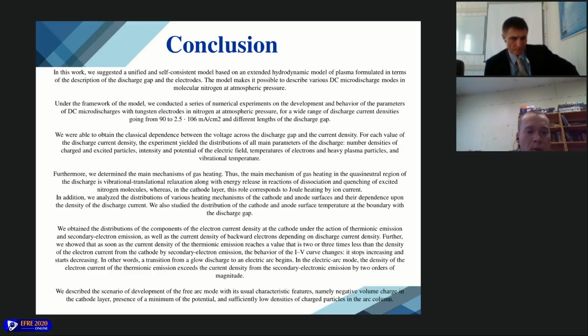We obtain a classical dependence between the voltage across the discharge gap and the current density. For each value of the discharge current density, we find all main parameters of the discharge: number densities, charged and excited particles, electric field distribution, potential distribution, temperature of electrons, heavy particles, and vibrational temperature. We determine the main mechanisms of gas heating.